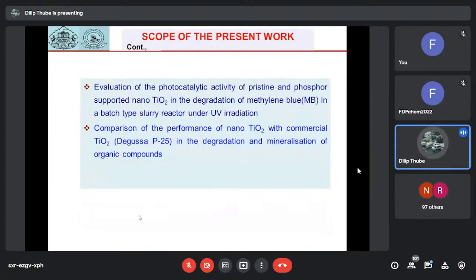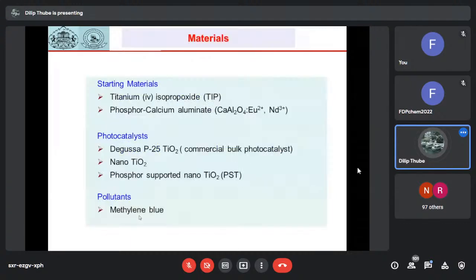as well as the photocatalytic efficiency is evaluated by using an experiment specially designed. Evaluation of photocatalytic activity of pristine and phosphor supported TiO2 material in the degradation of methylene blue in a batch type slurry reactor under UV radiation, and the comparison of the performance of TiO2 with the commercial TiO2 in the degradation and mineralization of the organic pollutants.